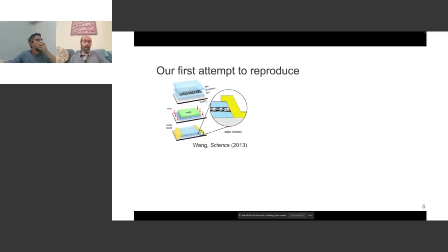And so the way that these samples are made, I mentioned that graphene is typically produced by putting tape on a surface, on a graphite crystal, peeling it off. Turns out you fold it together a number of times, then press the tape against some other substrate, peel it off, and you end up with a range of different thin layers of graphene. And if you take a good optical microscope, you can search this chip and you can find layers that in some cases are just one atom thick. And that actually was the key